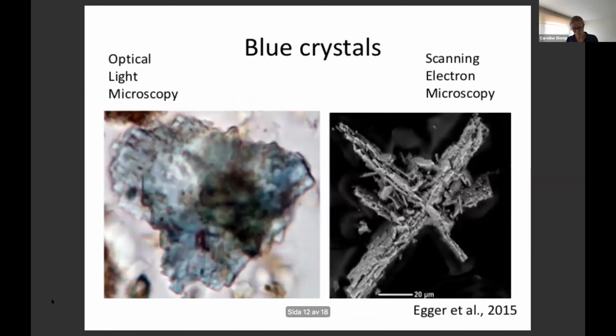Next slide, please. And another technique you can use is you can sieve the sediment, and if you have these large crystals, you can separate the Vivianite from the rest of the sediment, and you can look at it with optical light microscopy. You see here a blue crystal. So you can see we tried to not expose it to oxygen, but there was apparently a little bit of oxygen exposure leading to this blue color. And then we have on the right-hand side scanning electron microscopy images of a Vivianite crystal.